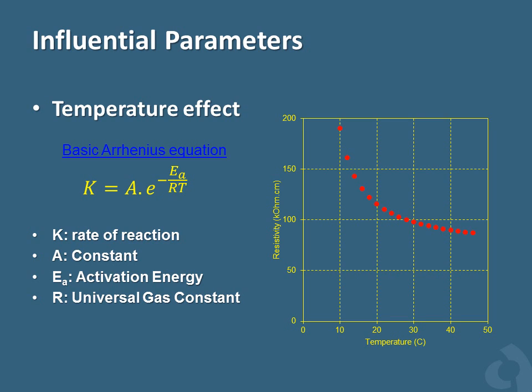The other influential parameter is temperature. In general, an increase in temperature decreases the electrical resistivity of concrete. This can be explained by the Arrhenius equation. In simple terms, an increase in temperature will increase the rate of ionic movements. More ionic movement means more electrical conductivity and lower resistivity values.